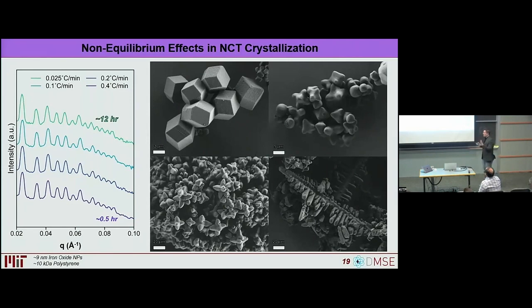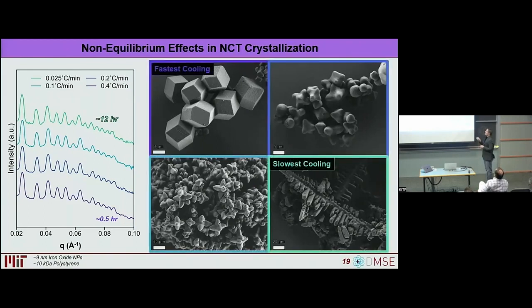And I said, Matt, that's fine. If you cool things down really quickly, you tend to get things that are more kinetic, things that are more dendritic, things that are a little bit outside of equilibrium. And he said, no, you don't understand. This was the rapid cooling, and this was the slow cooling. So if we cool these samples down over, say, 30 minutes, they will form the perfect Wulff polyhedra that we'd actually predict. If we cool them down over a day or more, we get these stellated dendritic structures, which is the exact opposite of what anybody would predict based on standard crystal nucleation and growth. So what exactly is going on here?